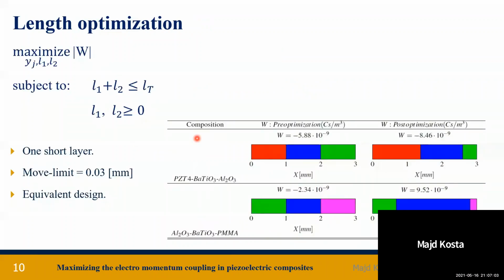And the first problem that we consider is length optimization. And here we aim to optimize the electromomentum coupling over the length of each layer, while the total length of the periodic cell and the materials are fixed. We observe that the optimal design has a relatively short layer compared to the other two. And this very specific short layer has, once again, the same property that has been found before, which means the lowest mass density and the lowest piezoelectric coefficient.